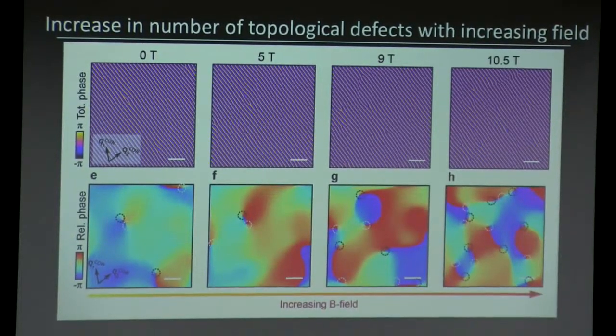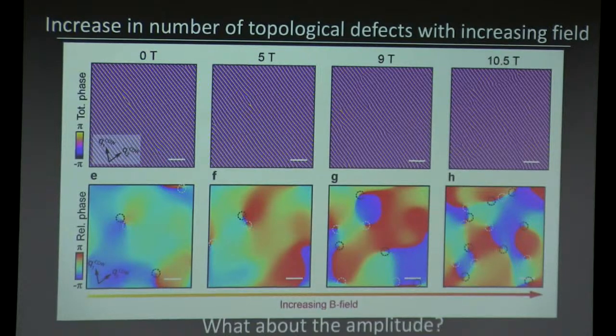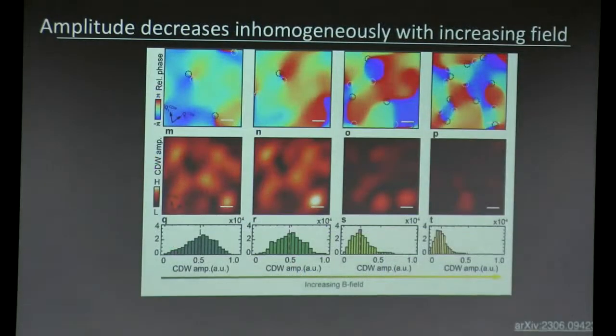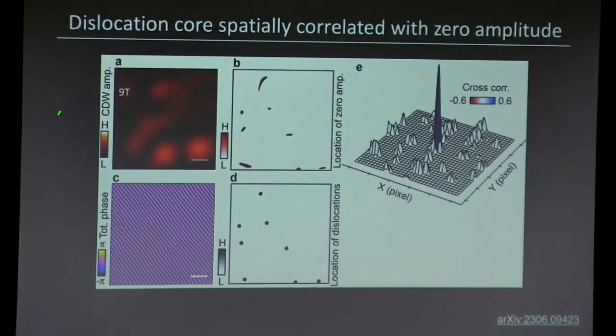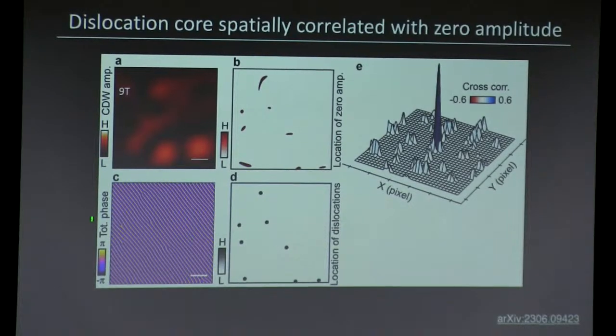So you have these pairs of dislocations with opposite phase windings that increase with increasing magnetic field. And the last question you ask is: do these dislocations actually kill your charge density wave order? To do that, you can look at the amplitude map and compare that with this map of the dislocations, and there's a direct one-to-one correspondence between the positions where the amplitude goes to 0 - these positions - and the locations of the dislocations.